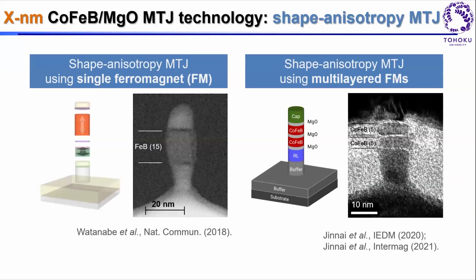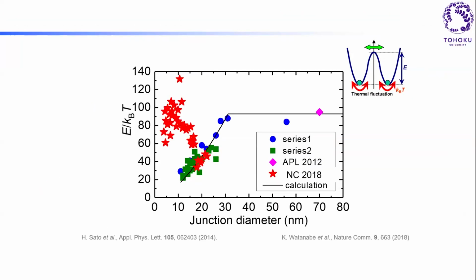And of course, making it is extremely painful, and we used to have a success rate of 1 in 1,000 or so. But now it's much better. And here are the results. We can go down to, let's say, less than 3 nanometers with more than 80 E energy over kBT. And that's good for many other applications.